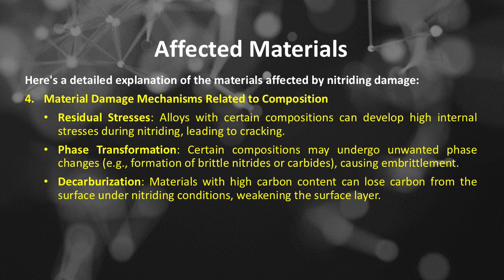Number 4 of the materials affected by nitriding damage is material damage mechanisms related to composition, including residual stresses. Alloys with certain compositions can develop high internal stresses during nitriding, leading to cracking. Phase transformation: certain compositions may undergo unwanted phase changes such as formation of brittle nitrides or carbides, causing embrittlement. Decarburization: materials with high carbon content can lose carbon from the surface under nitriding conditions, weakening the surface layer.